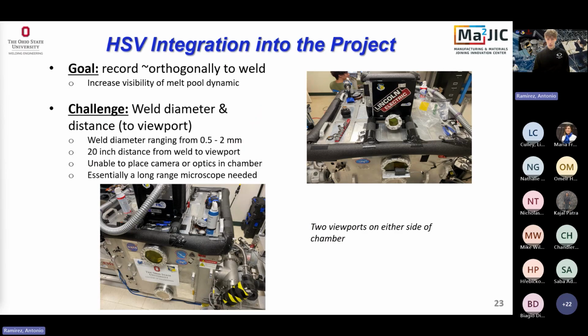Now, high-speed video is not very easy to get when you're looking at a vacuum chamber, because there's very limited viewports here. So about 2, maybe 3 viewports that we can use to see into the chamber to keep that high vacuum. So we have to make sure the laser illumination system and the camera are able to see into these. And the idea behind recording this is we want to record orthogonally to the weld so we can see the fluid flow and what's going on in the melt pool for model calibration.